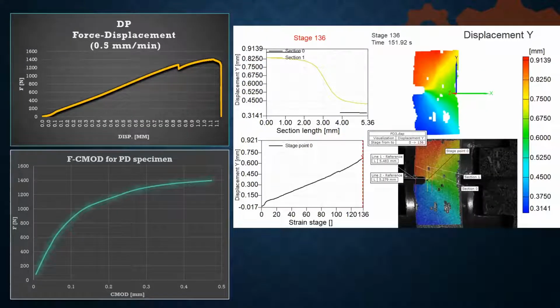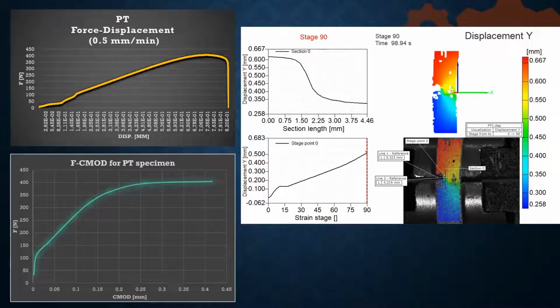On these graphs, we can notice a similar trend on the force-displacement diagram as on the force-CMOD diagram. What we can conclude from these diagrams is that the CMOD value is about twice as small at the approximate value of the force, as in the P-type specimen. And as for PT specimens, their CMOD value is close to the value of P-type specimens for a drastically lower force value. On the right side of the slide is the displacement area recorded by the Aramis system.